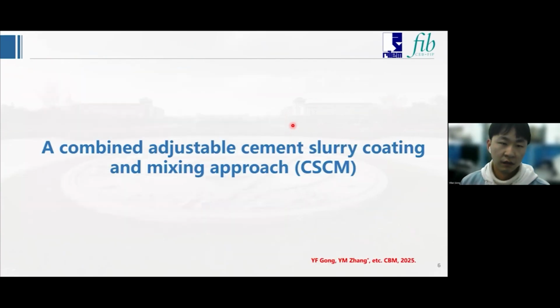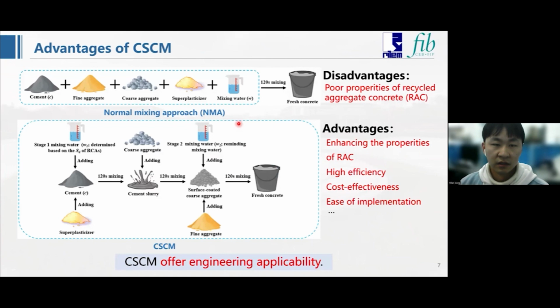In this case, we propose a combined adjustable cement slurry coating and mixing approach, the CSCM. Unlike the normal mixing approach, which mixes all the materials together, the mixing water is divided into two stages based on the saturation degree of the RCAs. The proposed CSCM effectively prevents the excessive absorption of mixing water by RCAs, enabling the flexible adjustment of mixing water based on the variation in aggregate SD.